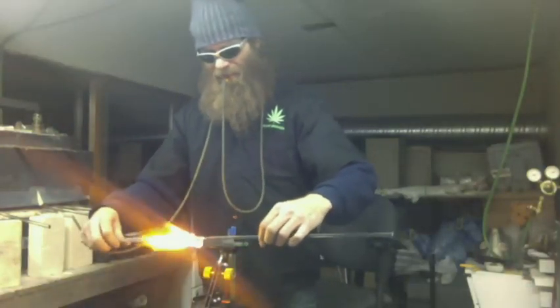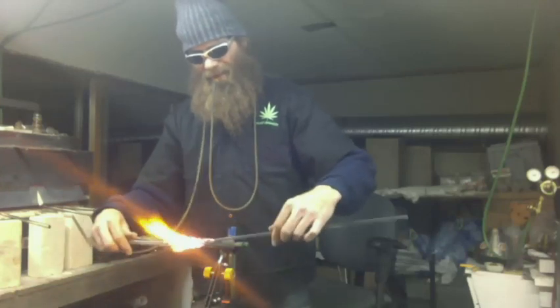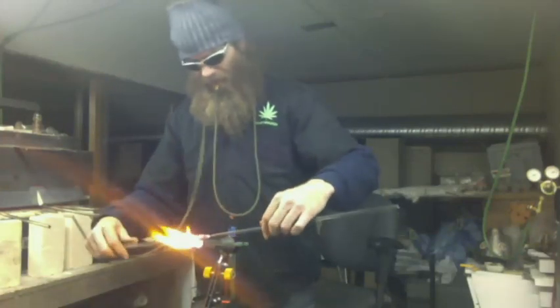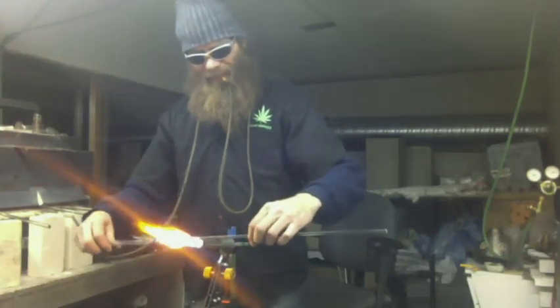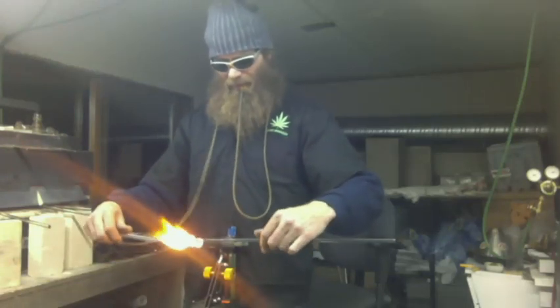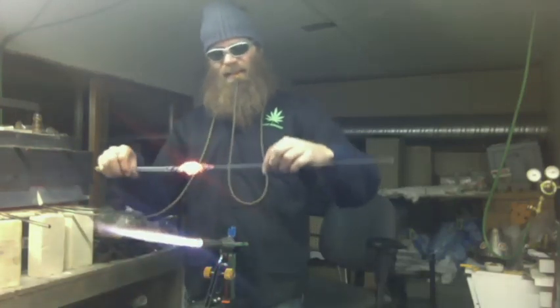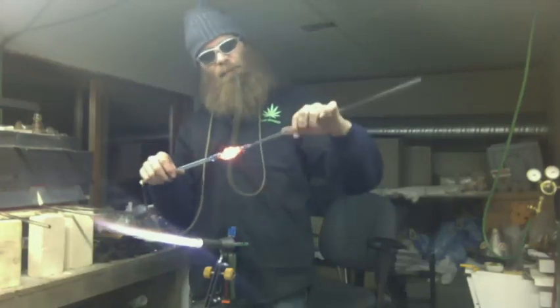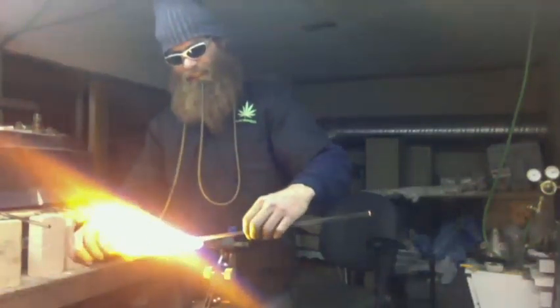For you glass blowers out there, I'll give you a couple tips in a minute on how I do the sleeving. Getting ready for it. It's necessary to put a clear tube on the end of your insert and on the end of your sleeve just to give it some buffer room at the beginning of your sleeve and at the end. So I always add a bit of clear onto both sides, and I think that's pretty key to save all your pattern.